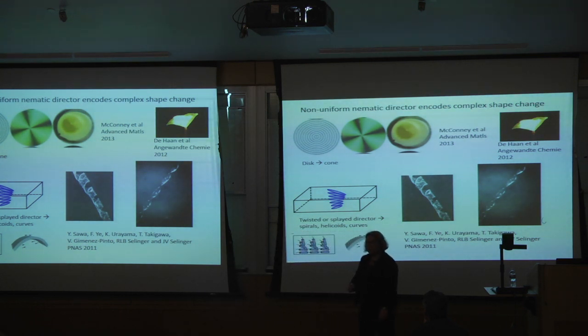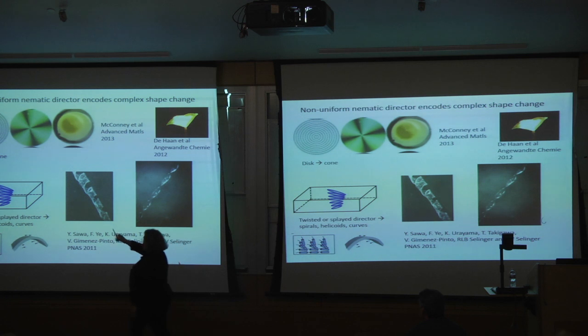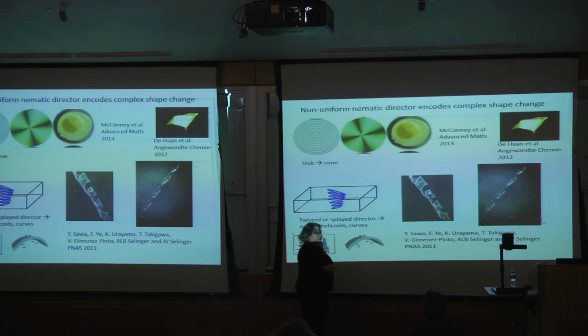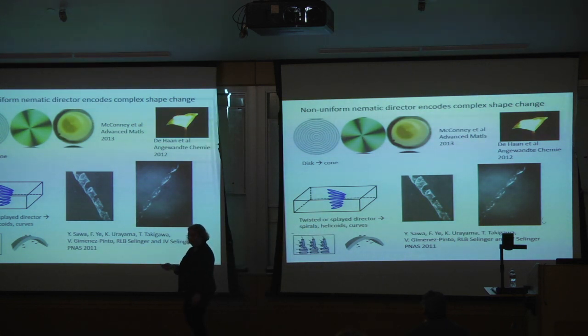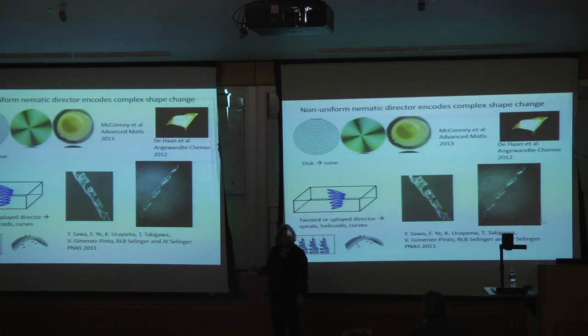We call this a +1 topological defect because if I take my pen and lay it parallel to the axis of the molecules, going around, my pen would rotate by 1 rotation in the plus theta direction, which is the counterclockwise direction. You can really see how stretched this image is, because those are supposed to be circles. Anyway, the +1 defect, when you actuate it, doesn't stay flat. It pops into the third dimension and you get a cone. That means that by putting this circular pattern into the nematic director, we have programmed a shape transformation from a disk to a cone. It's not a perfect cone; it has some roundedness at the tip.